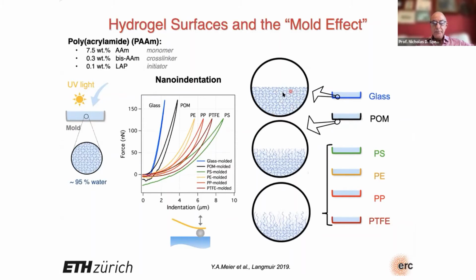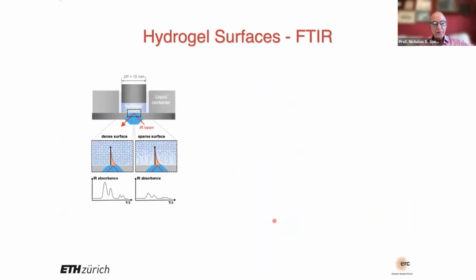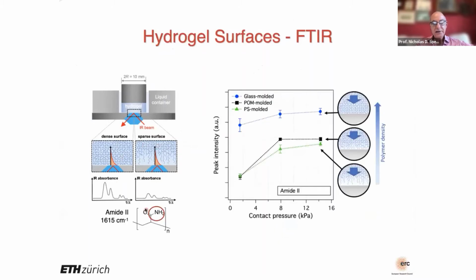So this is how Jian Ping Gong, and we believe, the surface of the hydrogel is when it's been molded against glass. So very few dangling chains, and then against the hydrophobic surfaces we have these dangling chains. And we've looked at this in IR as well. As you push these different terminated surfaces down onto an ATR crystal in IR, you get different behavior, and you start to see these amide signals changing in the case of the dangling chains, but they don't change in intensity in the case of the fully cross-linked gel. So the glass molded one doesn't change when you press it down. So this confirms what Jian Ping Gong has suggested, that against hydrophobic surfaces, we seem to get dangling chains.